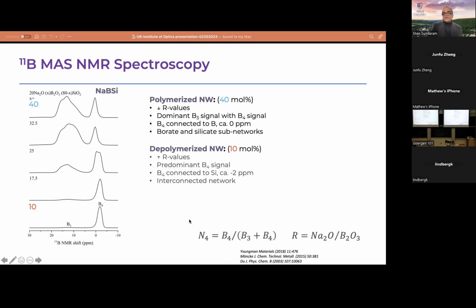Let me go back to the NMR spectra here. You will see me using two terms: one is polymerized network, and the other is depolymerized network. When you have 10 mole% of boron, you see high R values, and we start to see predominantly B4, which is 4-coordinated boron, in the structure, some of it connected to silicon, in a very interconnected network. When you go up to 40 mole% boron, we see lower R values, and a dominant signature coming from 3-coordinated boron and 4-coordinated boron in our glass structure. And so we see a borate and silicate subnetwork.